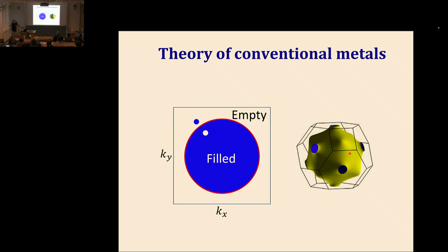The statement is, if the system was perfectly clean, which it isn't in real life, but sometimes these systems can be very clean, and if the temperature goes to 0 and the energy of our excitation goes to 0, asymptotically we actually have an exact excitation of the system, described essentially by injecting or removing a single electron. Or at least injecting or removing a single electron has a finite overlap, called the quasi-particle weight, with the exact excitation of the system. Again, from that very simple idea, you can actually calculate a lot of things.